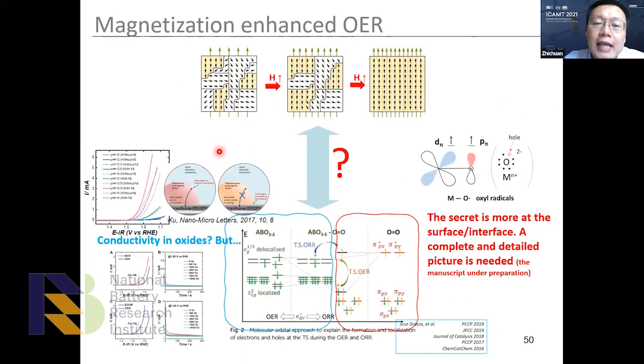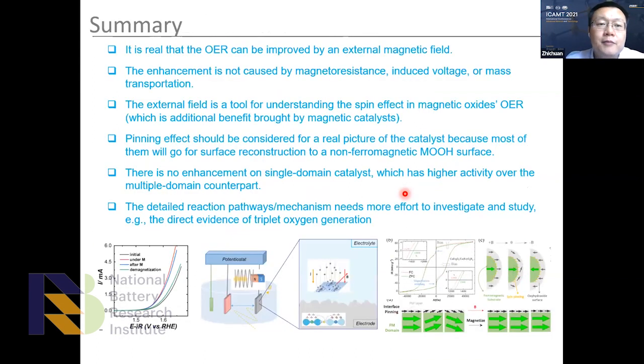Okay, so finally, I would say for magnetization enhanced OER, it is clear that spin played an important role for the triplet oxygen production, and the ferromagnetic oxides give an additional benefit in addition to the thermodynamics, right? However, to completely describe the surface, let's say what happened over there, we need to pay attention to the radicals. So now we are preparing the manuscript to further disclose the mechanism over there.